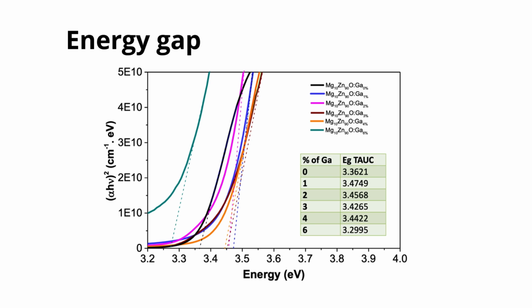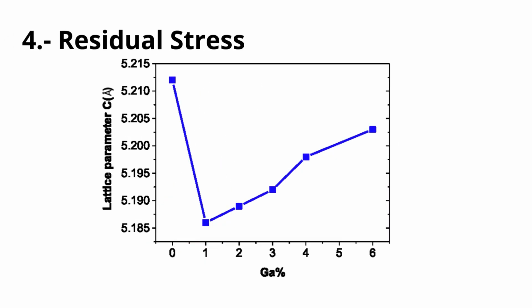So in the Tauc analysis, as can be seen in the energy gap table, the sample with the highest energy gap for these gallium doped samples is between 1% and 2%, with estimations of 3.47 electron volts and 3.45 electron volts for the energy gap. The fourth step is residual stress. It indicates that the smallest lattice constant is presently between 1% and 2%. This directly influences the energy gap calculated by Tauc. There is a correlation here.